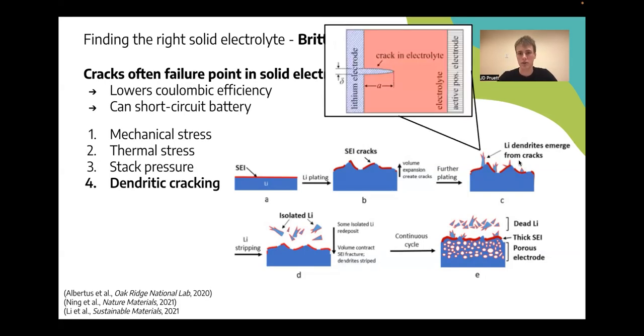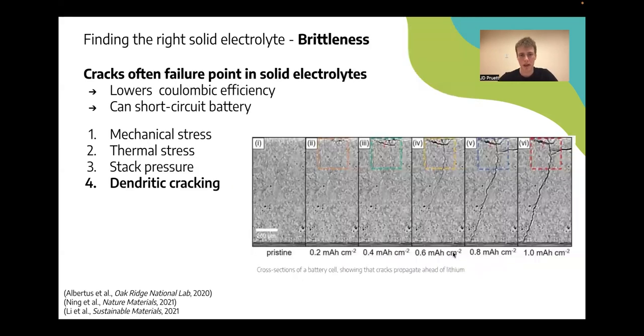And here's a nice little image of what that shows. So we see here a lithium dendrite penetrating into the electrolyte, causing a crack. From there, things only get worse. We can have bits of lithium that actually get trapped in the solid electrolyte and never redeposit onto the anode. And this basically just kills the capacity of our battery. And this is what it looks like in TEM. So as you can see, as we cycle more current through the battery, we get these long cracks in the solid electrolyte.